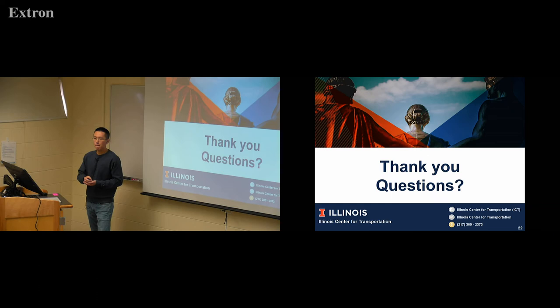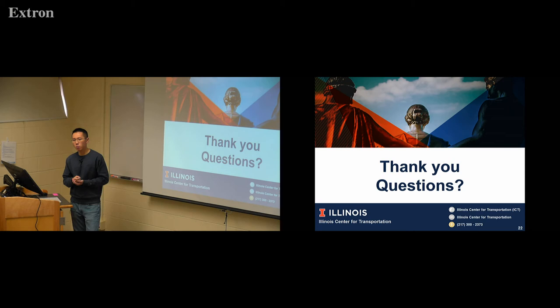A follow-up question. You just mentioned that FI is pretty insensitive to aging. So Gf, which is the fracture energy. FI is calculated by dividing the fracture energy by the slope times the coefficient, which we use is 0.01. So your fracture energy almost remains constant, but your slope increases, which induces a decrease in your flexibility. So you are saying it is the slope that plays the main role in describing the aging of the structure. Yes. Not the fracture energy. Mostly. Yes.